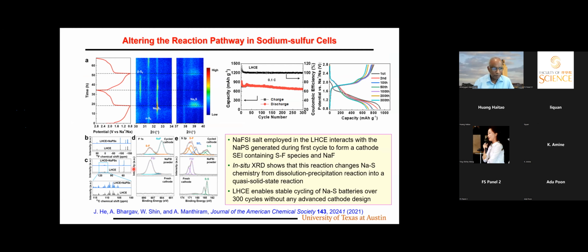We have also done a lot of characterization, both with NMR as well as with XPS. So it turns out the NaFSI salt we use in the localized high concentration electrolyte reacts with the polysulfide formed initially during the first cycle to form a cathode SEI containing sulfur fluorine species as well as sodium fluoride. That's what these characterizations show, NMR as well as XPS. So this is what is really happening when we use this electrolyte, that is electrolyte salt, the polysulfide interaction. So that leads to the formation of these. Once it is formed, that seems to change the reaction chemistry pathway from a conventional dissolution precipitation reaction into a quasi solid state kind of reaction, because we don't see the polysulfide formed after 1 or 2 cycles. So that it gives much better cycle life with high capacity in the sodium-sulfur cells.